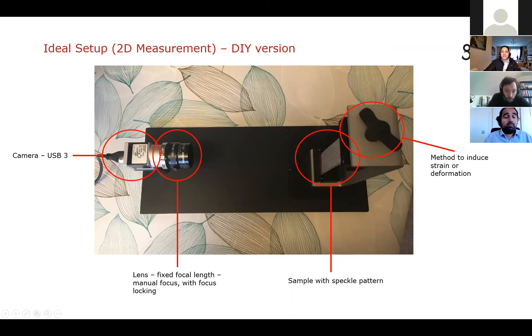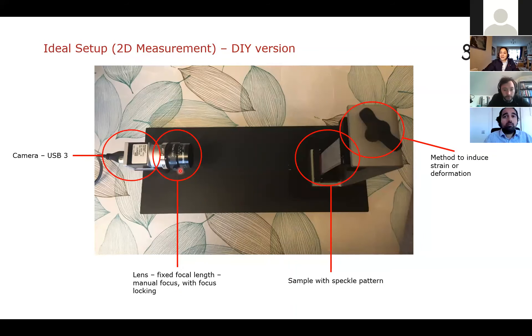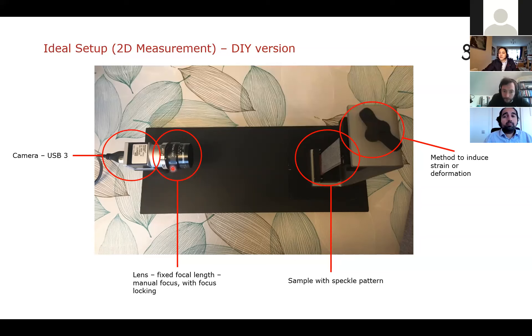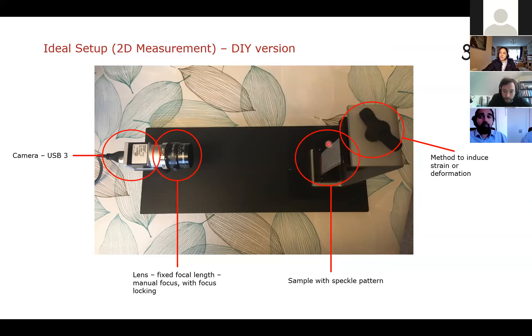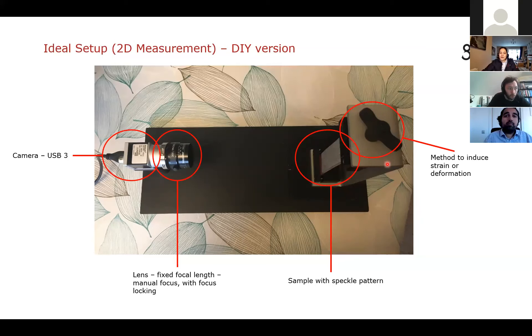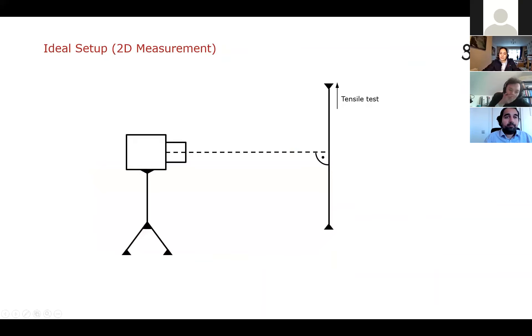I've got a fixed focal length lens where it's got these locking screws so I can lock the focus so that doesn't change in the middle of a test or test to test. And then I can change the aperture and that can be locked as well. This is then mounted on this rig so it's always perfectly perpendicular to my sample. This is just a simple rubber tensile test with a speckle pattern, but because the part's rubber, I can deform it very easily with this small plastic handle. But of course, most of the time you'd want like a proper test machine to deform the sample.